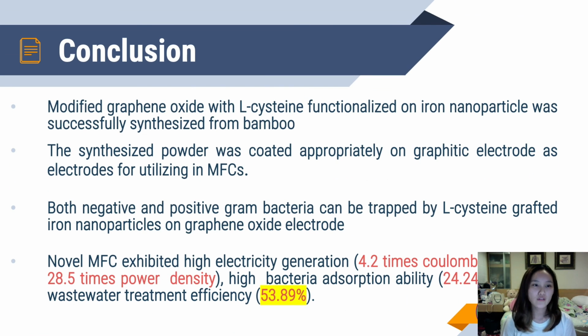In conclusion, modified graphene oxide with L-cysteine functionalized on iron nanoparticles was successfully synthesized from bamboo. The synthesized powder was coated appropriately on the graphitic electrode for use in the microbial fuel cell. Both gram-negative and gram-positive bacteria can be trapped by the L-cysteine grafted iron nanoparticle on graphene oxide electrode. The novel microbial fuel cell exhibits high electricity generation, with 4.2 times Coulombic efficiency and 28.5 times power density, high bacterial adsorption ability, and high wastewater treatment efficiency.